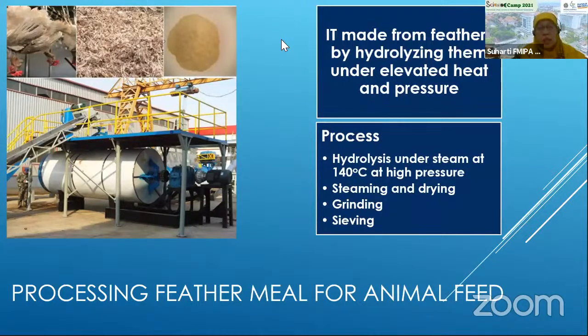Basically, mostly it's done through hydrolyzing the feather under elevated heat and pressure. That means we increase the pressure and heat step by step. Because it's a many-step process, I just give the general process. It hydrolyzes under steam at 140 degrees at high pressure, and then after that they continue steaming it at even higher